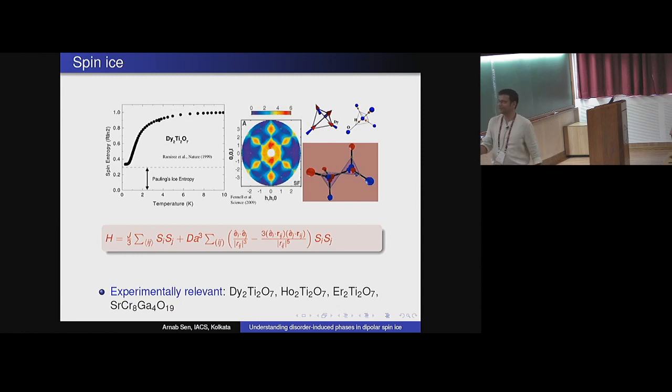and you look at the size of your magnetic moment, you realize that your magnetic moments are sort of 10 Bohr magneton, so they're basically 10 times larger than most magnetic moments that you would encounter, and that actually means that the dipolar interaction here is sort of 100 times larger than most dipolar interactions that you would encounter in a magnetic system. And if you then calculate the numbers, these dipolar interactions are extremely significant, and they are basically as significant as